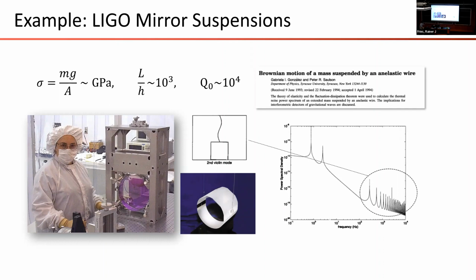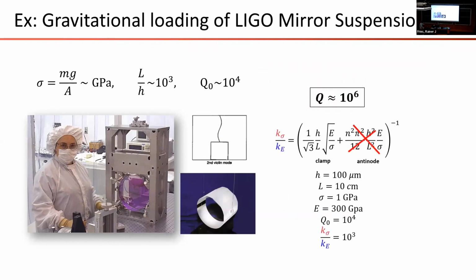So a typical suspension spring in a LIGO vibration isolation system has a tensile stress of a gigapascal. The suspensions themselves have aspect ratios of 10 to the 3, and the internal quality factor for most Class A materials is like 10 to the 4. And so the string violin modes of these suspensions are diluted, via dissipation dilution, to 10 to the 6. It's cute. And in fact, they understood that a long time ago, and they did it on purpose.